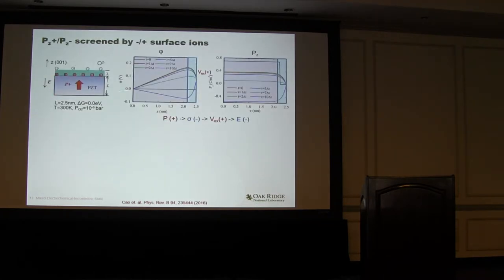We start with a 001 prototype PZT material without a top electrode, but with the existence of surface charge. When the polarization is pointing upwards, it creates a positive polarization charge, which attracts negative surface charge for partial compensation. And we plot the electrical potential and polarization evolution as a function of thin film thickness. This is the surface layer, and this is the bulk ferroelectric. We find that